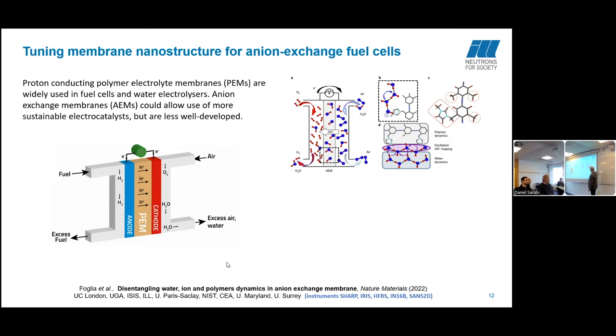And it's been studied before using neutrons. The thought is that transport is largely determined by bulk water, vehicular transport, where the hydrogen just gets carried along with bulk water. And also hopping, when a hydroxyl ion hops from site to site, either through proton transport or the actual hydroxide ion hopping from site to site. And then, of course, there's the dynamics of the polymer backbone itself.